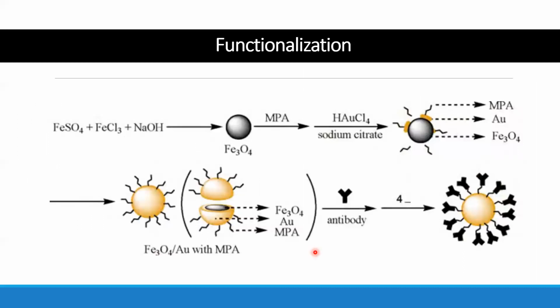So now let's jump into the functionalization part. As we mentioned before, the MPA compound plays a key role in the functionalization of these nanoparticles. So in order to functionalize the nanoparticle, the carboxyl group of the MPA composite surface was activated with NHS under the catalysis of the EDC compound. After this activation, the carboxyl group can react with the amino group of the protein of the antibody. Then desired concentration were introduced into the nanoparticle solution to conjugate the nanoparticles and enable the antibody detection.